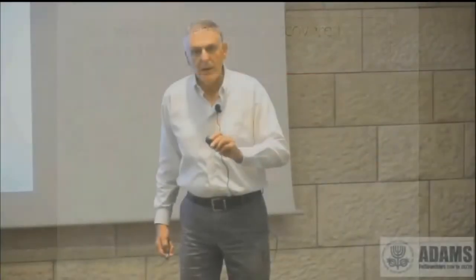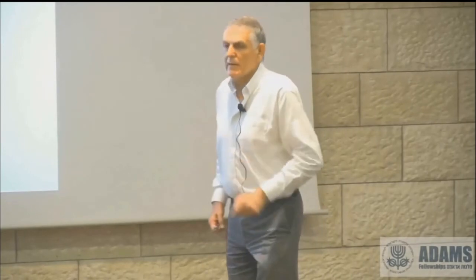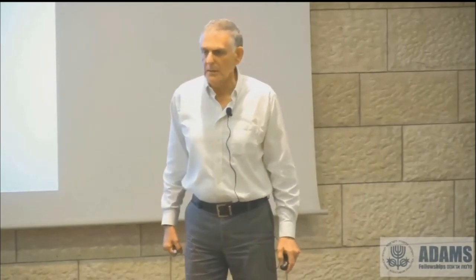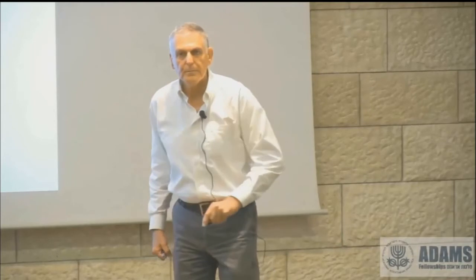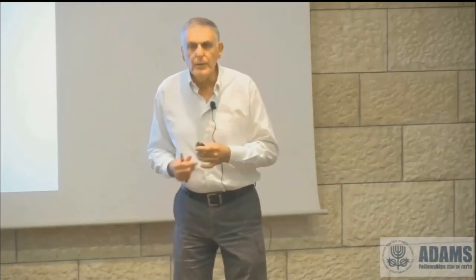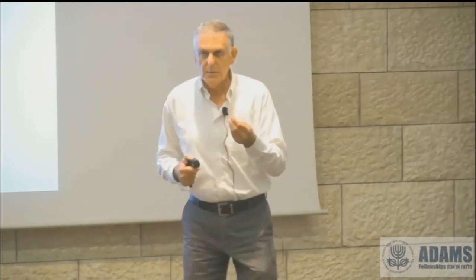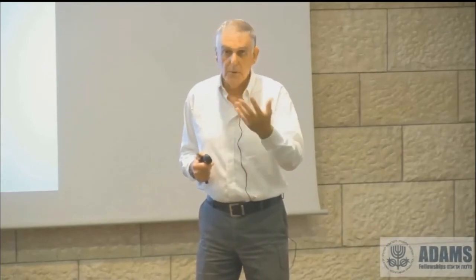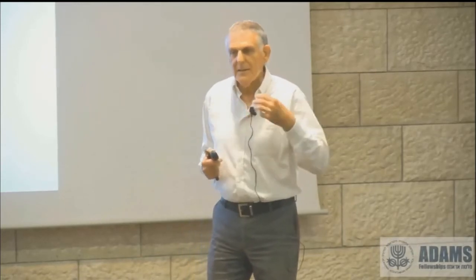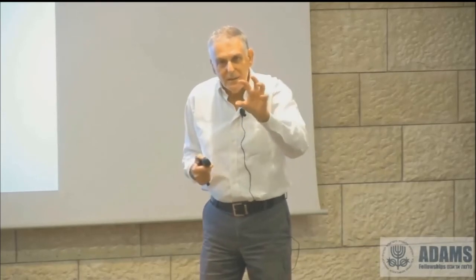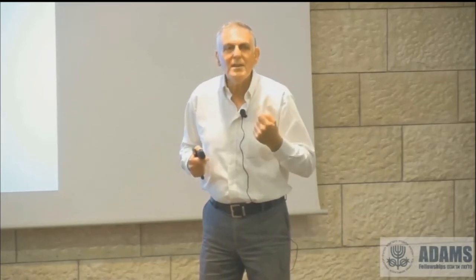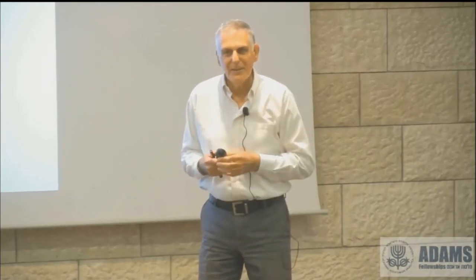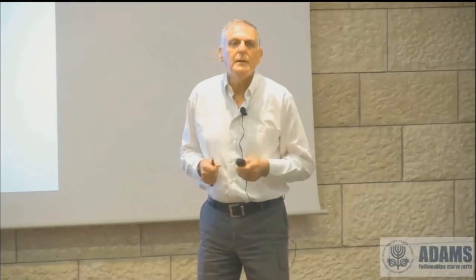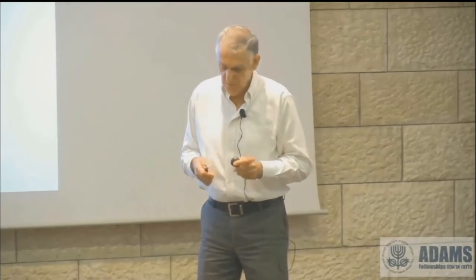And this is now becoming subjective. Number one, quasi-periodic materials had to be discovered by TEM, transmission electron microscope, because they were very small. If you take X-ray diffraction of a material which is quasi-periodic, and it's polycrystalline, you have many little crystals, and instead of points, you see rings. And you cannot see the five-fold rotational symmetry. You lose the rotational symmetry. So it had to be done by TEM. So TEM is rule number one.